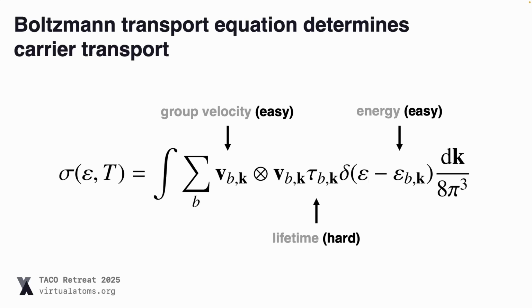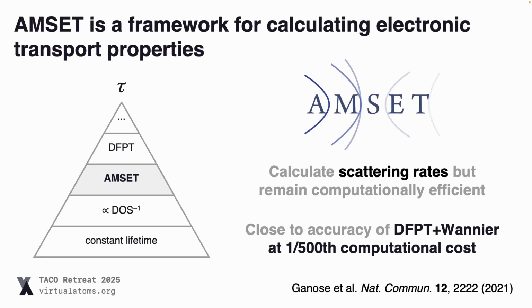And so there's been a whole range of methods proposed for calculating the lifetime of electrons in solids, going from just using a constant lifetime and hoping that this gives you some sort of reasonable results. But obviously when you do that, the results that you get can be scaled arbitrarily according to what lifetime you pick. There's techniques such as the inverse density of states approximation, where you say the lifetime is scaled versus the inverse density of states, which makes sense physically. If you have a larger density of states, you've got more states available to scatter into, so maybe your lifetime will be lower. But again, you still have to pick a reference lifetime, and so your results can be arbitrarily scaled again.